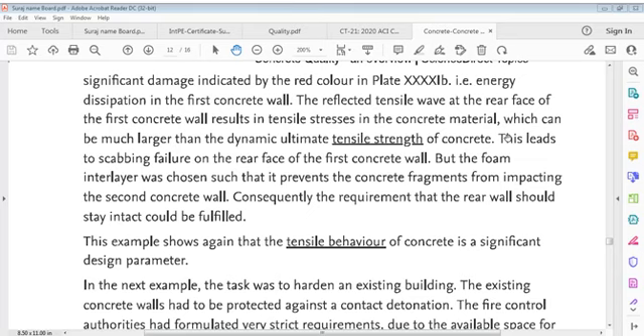So we can say, as we said, the reflected tensile wave at the rear face of the first concrete wall results in tensile stresses in the concrete material, which can be much larger than the dynamic ultimate tensile strength of concrete. This leads to scabbing failure on the rear face of the first concrete wall, but the foam interlayer was chosen such that it prevents concrete fragments from impacting the second concrete wall. Consequently, the requirement that the rear wall should stay intact is fulfilled.